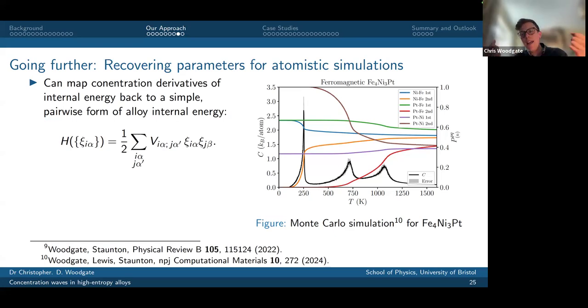And typically, okay, we were talking about range of interactions earlier. Typically, you find that these interactions are fairly short range. So you're talking the first handful of coordination shells before they tail off. And then what you can do is you can infer, you can look at the phase diagram across all regions because the Landau theory is only valid for inferring initial orderings.